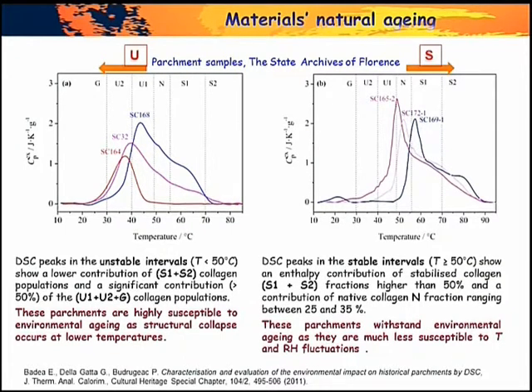Another observation, which is also very important, is that the natural environment deterioration generally produces this kind of, how to say, off trend. That means the moving of peaks towards higher temperature. That is, when aging, the tendency of collagen is to stabilize itself. Of course, some part of collagen becomes gelatin and other part of collagen deteriorates in an irreversible way, so we can no longer detect it using micro DSC, but we can quantify this collagen by taking into account the references.